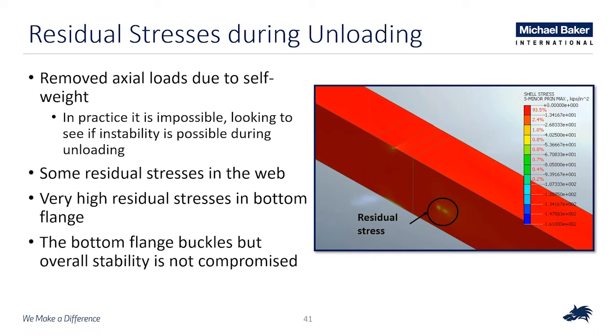And the second concern was the formation of residual stresses. We were wondering if a large amount of residual stresses were going to form in the inboard web plate that would create a buckling problem during the unloading, or maybe a localized instability. The analysis revealed, after removing those axial forces that we put in the initial step, although in practice it's impossible to remove all the axial forces, and in this case we basically wanted to go all the way to see if there were any issues, that very small residual stresses really form on the web plate, and where they formed, they were localized to the areas near the crack tips, or that particular area near the connection to the gusset plate.